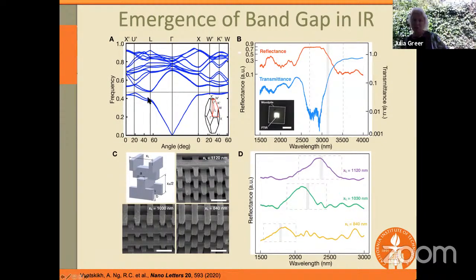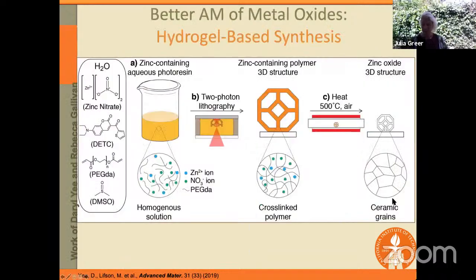So here are some simulations that show the dispersion relation for titania. And here's some real experimental data that shows the reflectance at particular wavelengths. And what we're discovering is that as we're shrinking the periodicity in these woodpile architectures from a little over a micron to a micron and below a micron, you can see that this reflectance peak shifts more and more towards the mid-IR range. And so you can see that it's possible to use these additive manufacturing processes to elicit a photonic response as well. Now, this whole acrylate-based chemistry that I showed you works very well, but it's a bit toxic. So the acrylic chemistry is not exactly very good for the environment.